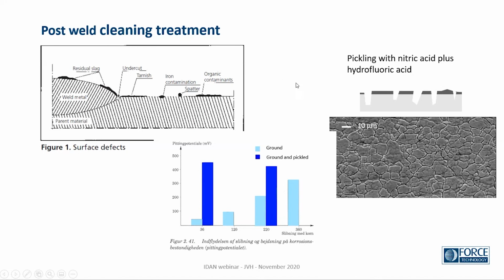This is just an illustration of the different problems we could have with contamination and oxides, which would be cleaned away if we do a pickling. You see, the drawback of pickling is that you get on a microscale a more rough surface because the acid attacks the grain boundary slightly. So we don't have the same as a polished surface after pickling.